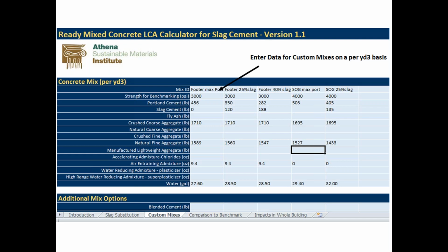Now we're also looking at using slag in this. So how is slag going to help us and improve this? So in the footer, we used one that was going to be 25% slag. We also looked at using a 40%. So depending on the time of the year, the application of where it's going on to, the region of where we're at, we may be able to use higher amounts of slag as the temperatures change. So slag cement likes heat. So if there's heat or curing being added to it, you can use more amounts of slag into that mix.